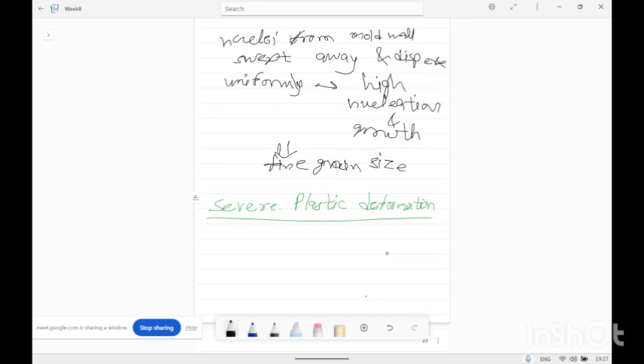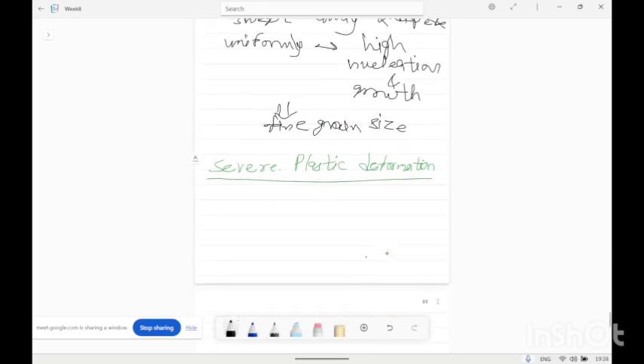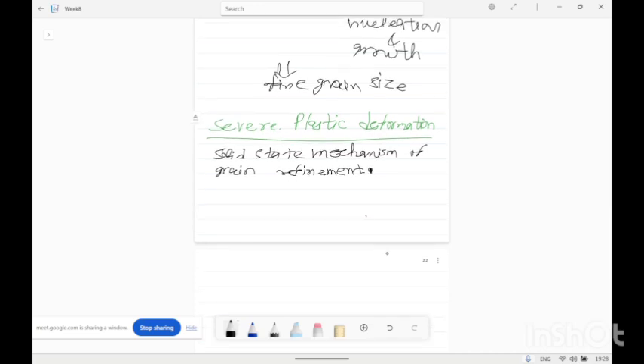So what is severe plastic deformation? All the other processes which we studied earlier are liquid phase processes, but severe plastic deformation is a solid state grain refinement mechanism, in which a part is subjected to severe plastic deformation to a much higher level that leads to dynamic recrystallization.